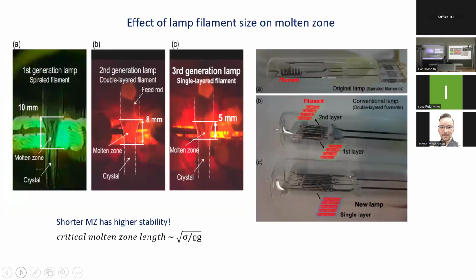So now you could see the design of the halogen lamp is the most important part. This is called the filament, it's the heating element. The thickness of this heating element roughly corresponds to the molten zone length. In the first generation, it was a spiraled or rounded filament, and it produced a relatively large molten zone, about 10 millimeters. If we grow the same material using the modern lamps, it's a single layered filament, and you see the double reduction in molten zone length, down to 5 millimeters.